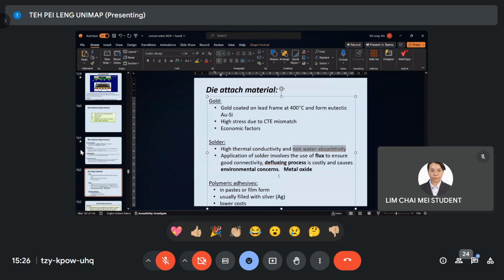But as I said, when solder is exposed to the air, to the oxygen, you will form metal oxide. If you form metal oxide, when you do the soldering you need to use flux to remove the oxide layer. After the flux has reacted, you must clean it away. So you must have this defluxing process, so it's very costly. The defluxing, as I said, uses warm DI water, right? After you wash it, the water cannot be let go straight to the drain, because you have chemicals inside. So it's also an environmental issue.